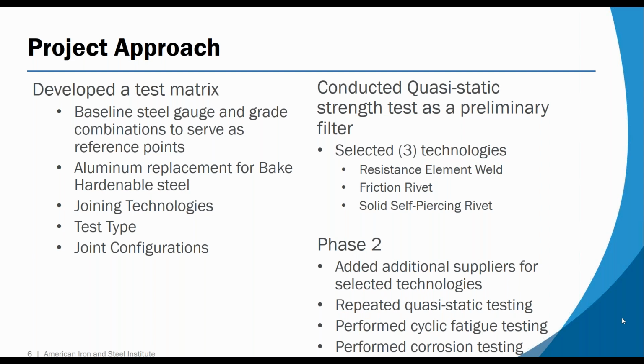And I'll speak more about these technologies in a moment, but we settled on resistance element welding, friction riveting, and solid self-piercing rivets. Going into phase 2, we took those 3 technologies, and for 2 of them, we added a second supplier so we could compare variations within the technology. Then we repeated the quasi-static testing to both include the new supplier's products as well as check the calibration on our existing suppliers. Then we took all of them through both a cyclic fatigue test and a corrosion test to finish the evaluation.